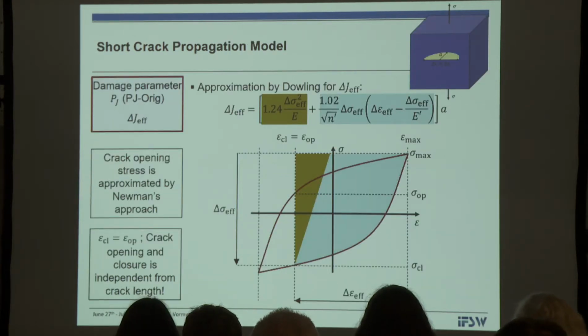The crack driving force: we have chosen to apply Dowling's version of the cyclic J integral, and there are nice formulas which are so easy that you can perform calculations also for 1,000,000 cycles. This formula simply applies for a semicircular crack in an infinite body, and it consists of that part in the brackets here where mechanical quantities such as stresses and strains appear, which are the stresses and strains in the situation without crack, and a is simply the radius of this semicircular crack.